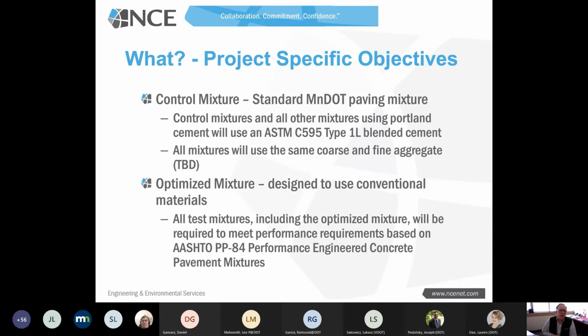So in more detail yet, the control mixture is going to be a standard Minnesota DOT paving mixture. All of the control mixtures and all the mixtures that use Portland cement are going to be using the C595 Type 1L blended cement, which is going to be 10% limestone. So no ordinary Type 1 Portland cement will be used in any of this construction. All the mixtures we're going to prepare are going to use the same coarse and fine aggregates, probably in different proportions depending upon the cement that's used, but it'll certainly be the same material.